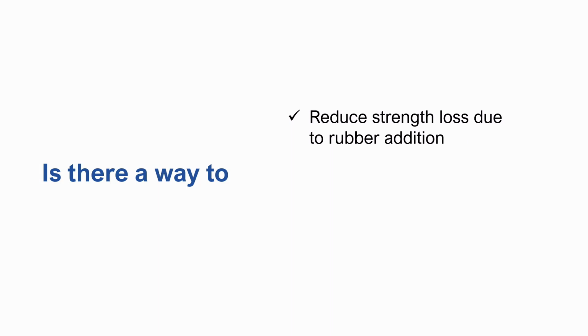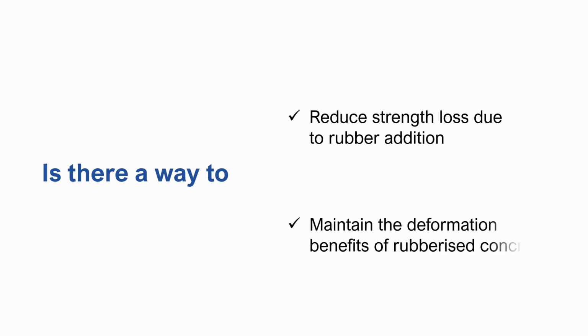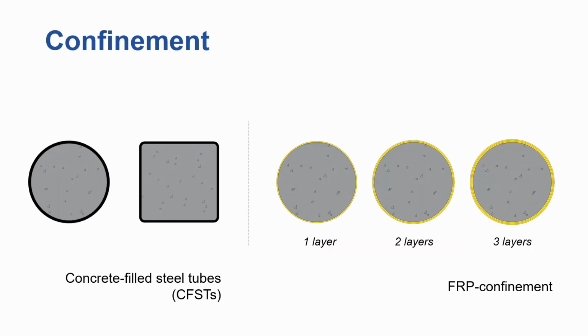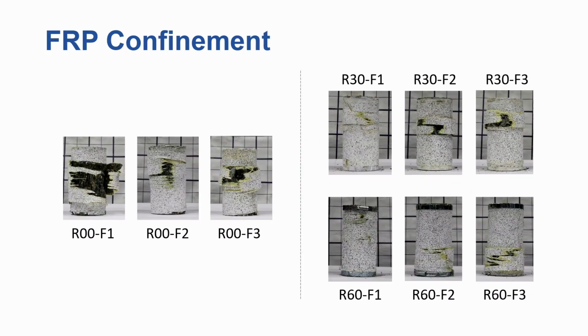So up to this point, we're like, okay, we fairly understand now the mechanical properties of rubberized concrete. Now, is there a way to reduce the strength loss due to rubber addition and maintain the deformation benefits we see from rubberized concrete? And that kind of led us to look at confinement. So we looked at concrete-filled steel tubes, circular sections and square sections, and we looked at another system of confinement by wrapping our specimens with fiber reinforced polymer.